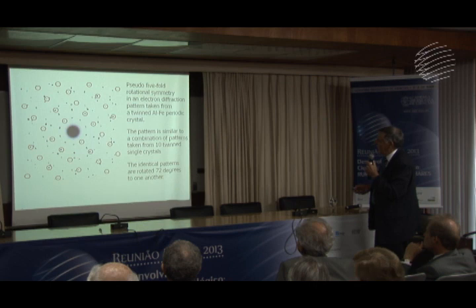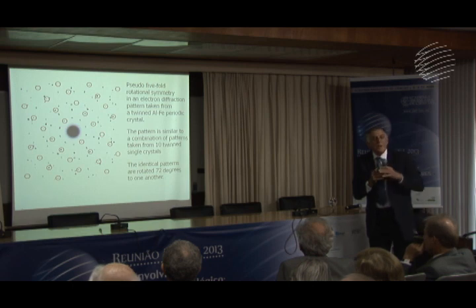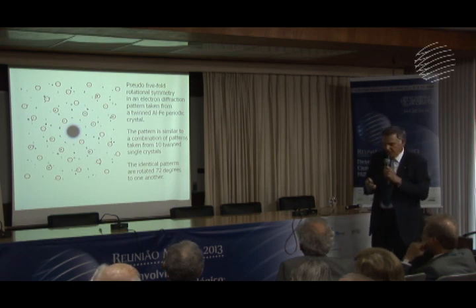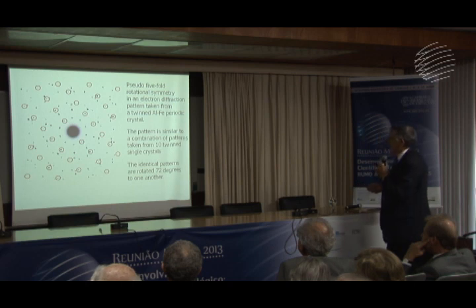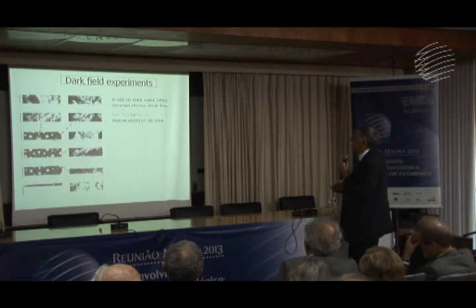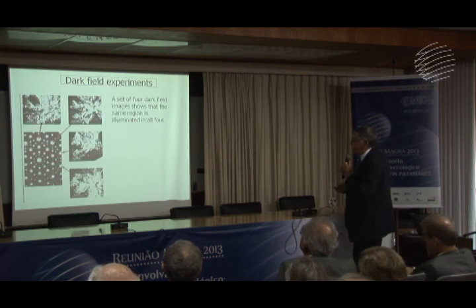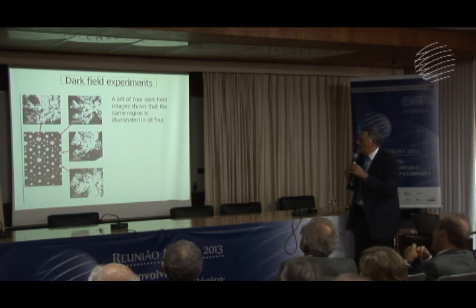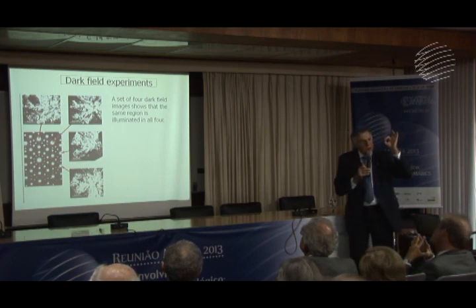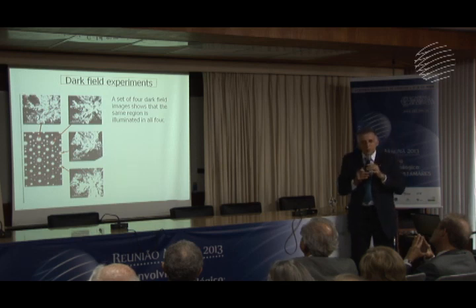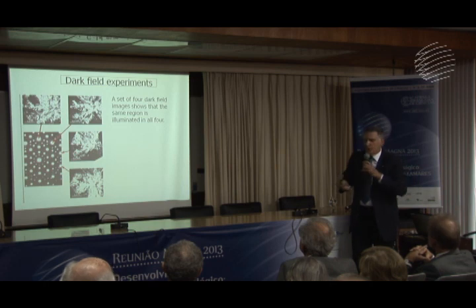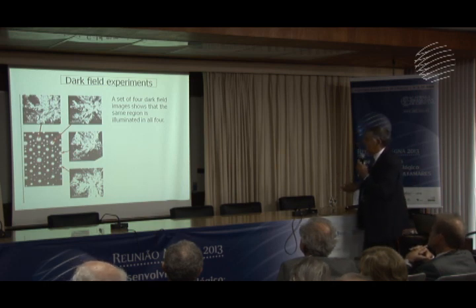And if you want to see just one of them, here is one. Okay, you see this periodic diffraction pattern, and there are five of them superimposed. This is what I had in my mind when I saw the five-fold rotation symmetry diffraction pattern. So I performed a series of experiments. I will just briefly go through them very quickly. These are called dark field experiments, and it means taking pictures through a diffraction spot, using just one diffraction spot, and if there are twins, then only a few twins contribute to each spot, and I should see only them. But everywhere I looked, I saw the whole crystal. No, there were no twins.